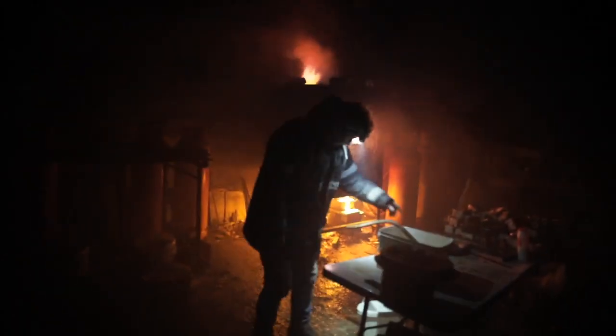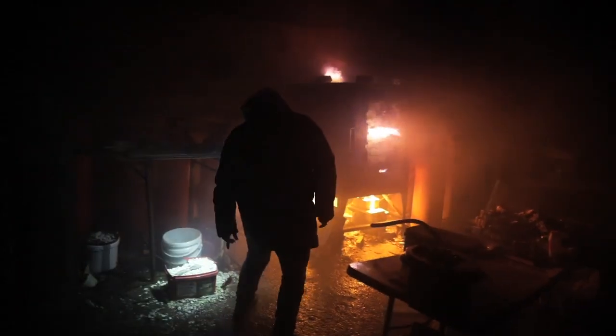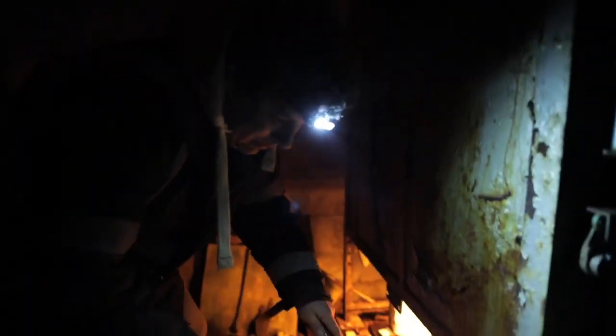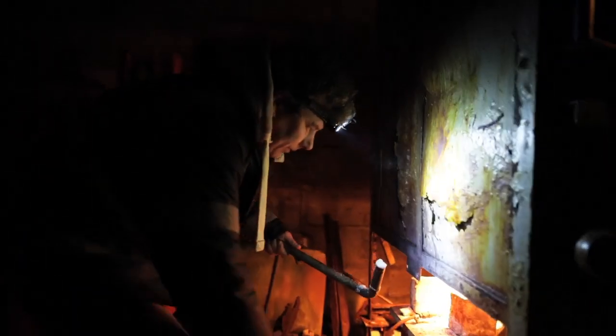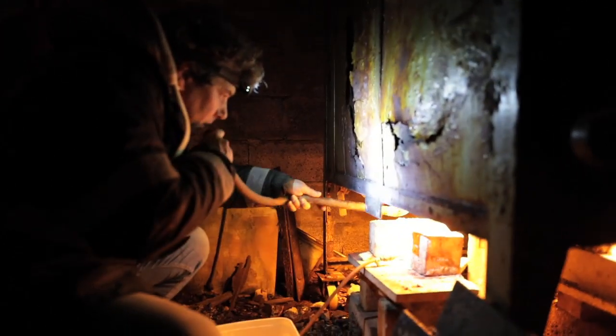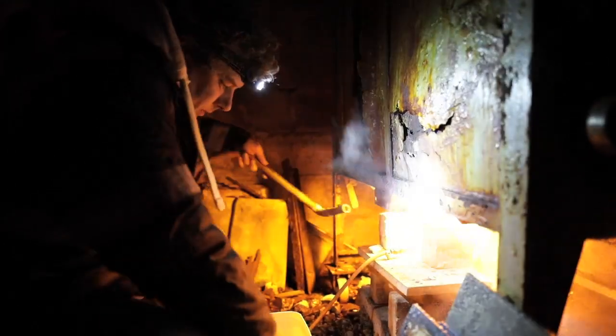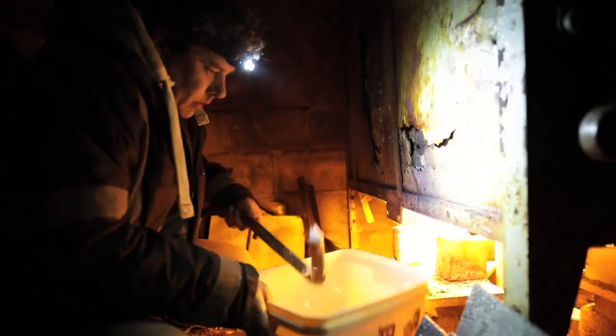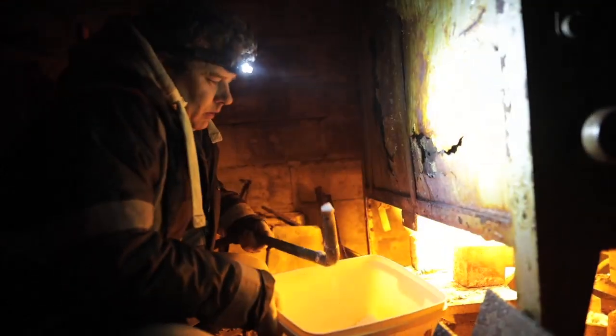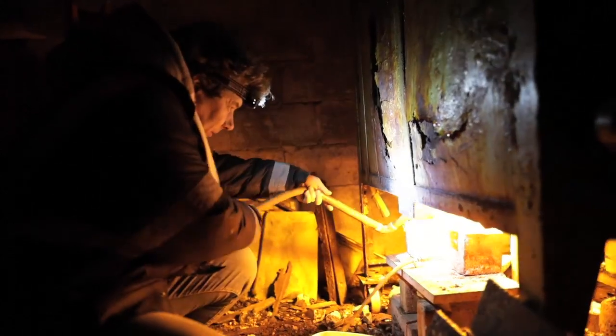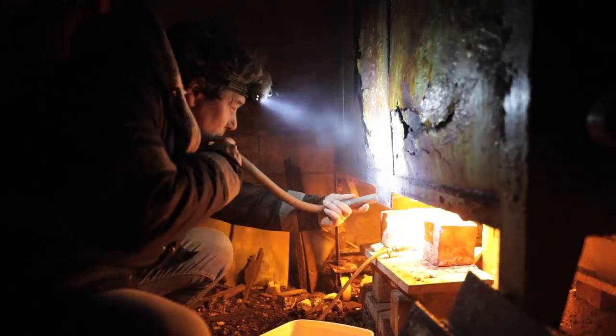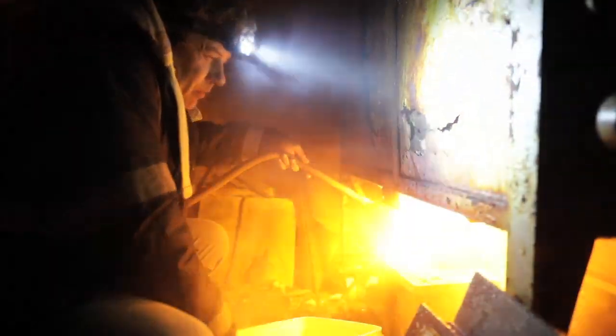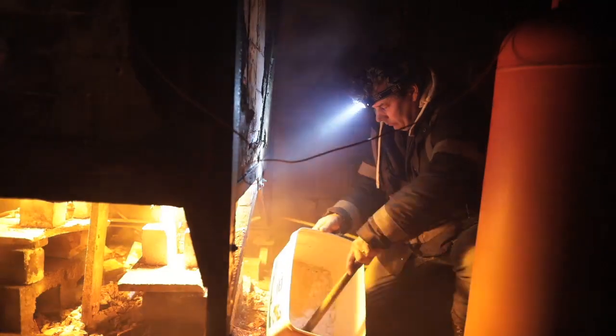When the kiln's at full temperature and the 1260 cone's just going, I have a copper pipe with a 90-degree bend on it and a bit of rubber hose. I fill it up to the elbow of the pipe with salt, and I put it under the floor of the kiln next to the burner, and with one puff I blow the salt into the kiln. In that way I'm hoping it will instantaneously fly over to all the pots where the flame's dancing over the top of them.